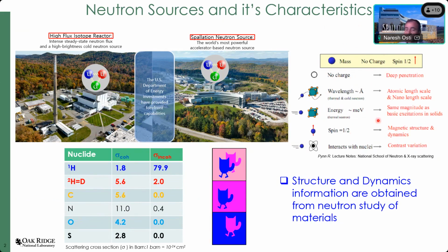Furthermore, the energy associated with the neutron is of the same magnitude as the excitations present in the material and the molecular dynamics that take place in the material. The neutrons also have a spin. Because of the presence of the spin, we can use neutrons to resolve the magnetic structure and dynamics. And most importantly, neutron scattering is totally dependent upon the scattering cross-section of the elements. If you look at this table, I have listed some of the elements and their neutron scattering cross-section. Hydrogen and deuterium have totally different incoherent neutron scattering cross-sections. Hydrogen has a very high incoherent scattering cross-section compared to deuterium.